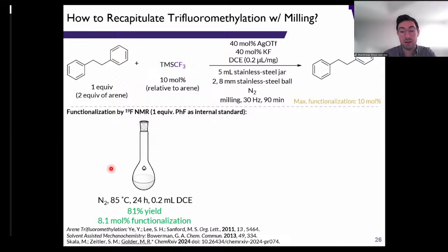trifluoromethylation reaction from Melanie Sanford's group that was reported about 15 years ago or so now. And we performed it both on bibenzyl in solution and under mechanochemical conditions. The idea here is that we're adding a gross excess of arene relative to our trifluoromethylating reagent. This gives us a max functionalization of 10 mole percent. So 100% yield would give us 10 mole percent. So if we set this up in solution under the standard conditions reported in the paper, we get about 8 mole percent functionalization, which equates to an 80% yield.